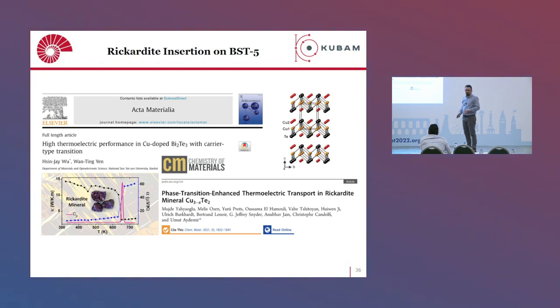And we also have tellurium. That's good because the main material also has tellurium, which means if there is any loss of tellurium, this can compensate for that loss as well. So these were two different aspects that we introduced into the structure, and we saw that this is really working quite nicely. We didn't publish this paper yet. We are just writing it. It's a very good idea.